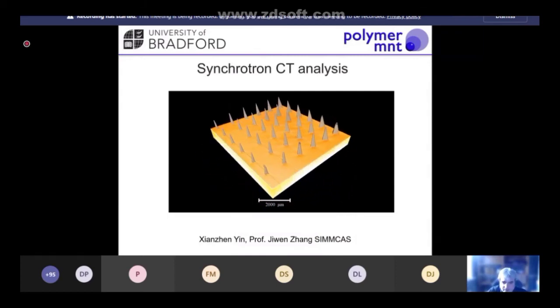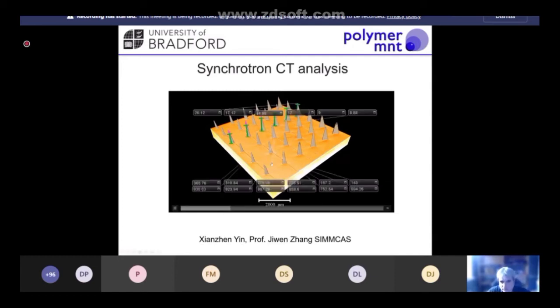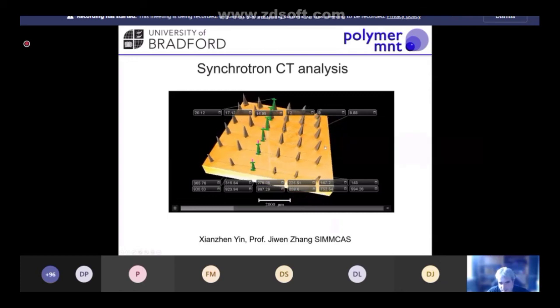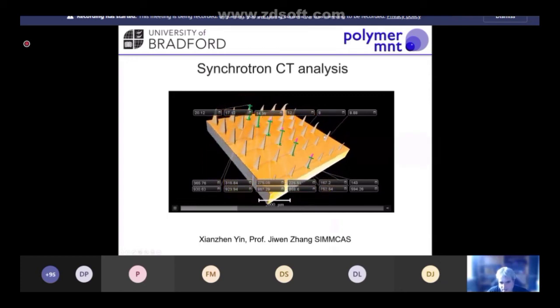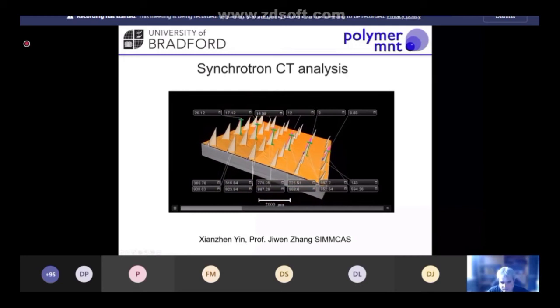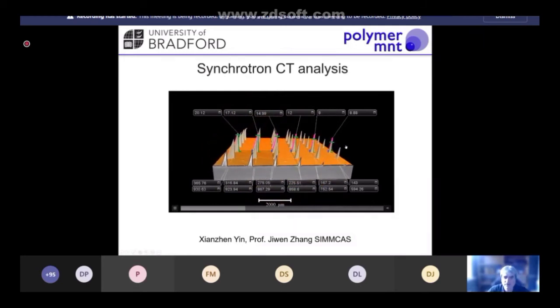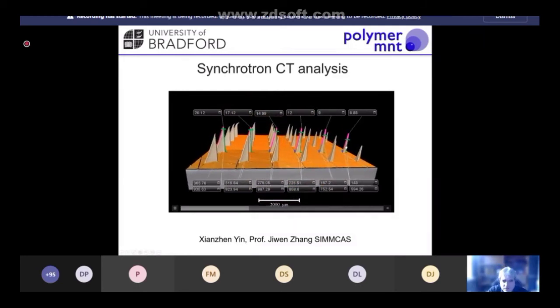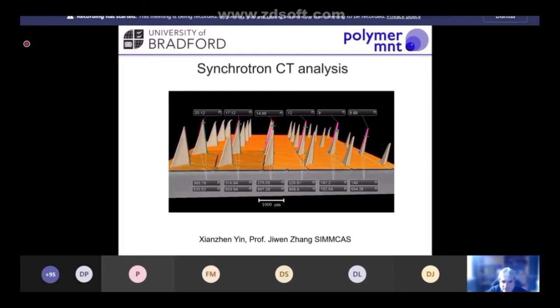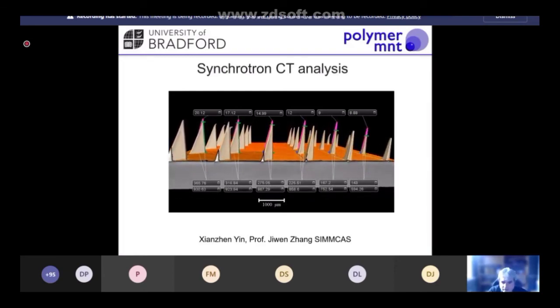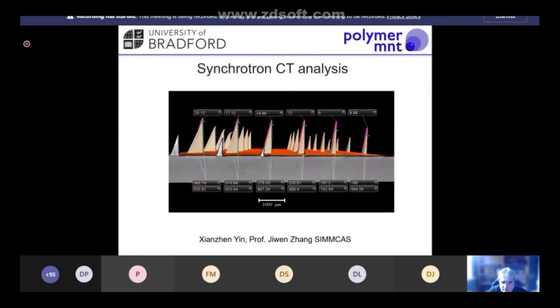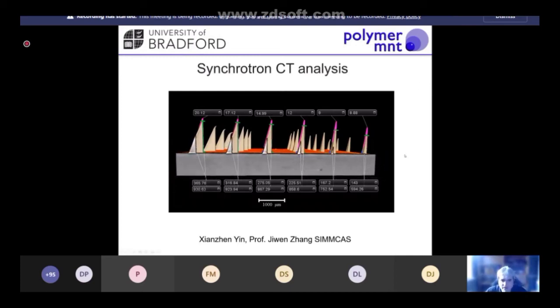For our sharp microneedle device, this is the device that was actually manufactured using the laminate-based mold tool. So you can actually see the split planes where the laminates neighbor each other. So we have this slight line that you can see clearly on the measurement that we've taken here. So with the CT analysis, we can get accurate measurements of each of the needles. We can look at tip radii, and we can compare that with what our design aspirations were. So we can make sure that we're making something that was as we'd expected it to be.